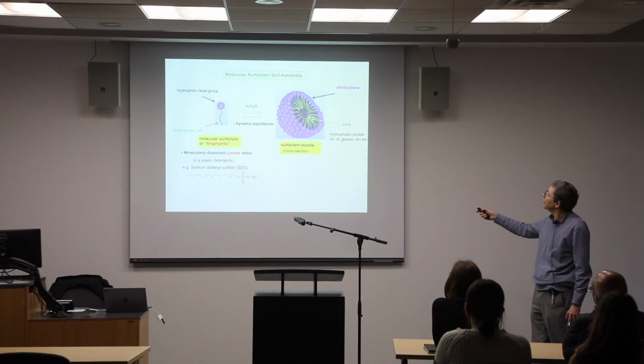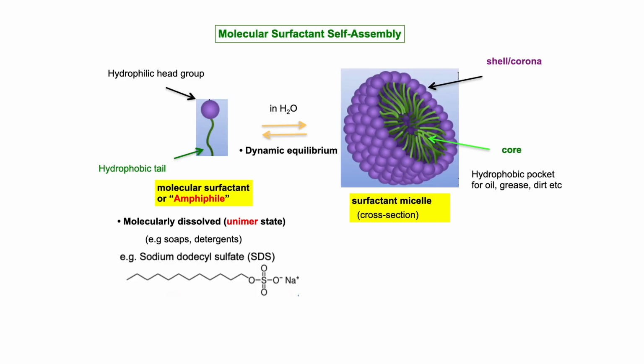So you have a core here, which is hydrophobic, and then around the edge you have a shell or corona, which is hydrophilic. And the beauty of these is if you have some grease or dirt - if you try and wash something with just pure water that's greasy or dirty, of course this doesn't work. But if you have these structures around, these have a hydrophobic pocket that will dissolve grease and dirt.